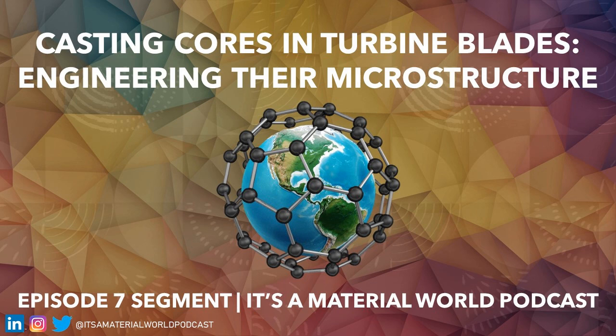Yeah, so the core manufacturers all have their own recipes. Some of them are highly proprietary, but I will say that it's about the composition, but then also how you fire it and how you drive cristobalite formation, which is a high temperature form of silica. And so that is basically defined by your processing conditions. And so every core manufacturer will have their low fire and their high fire process defined to carefully control composition and the microstructure. And one of the outputs, or one of the things that they measure, is high temperature flexural strength or modulus of rupture. And so those are the targets that they would try to hit.